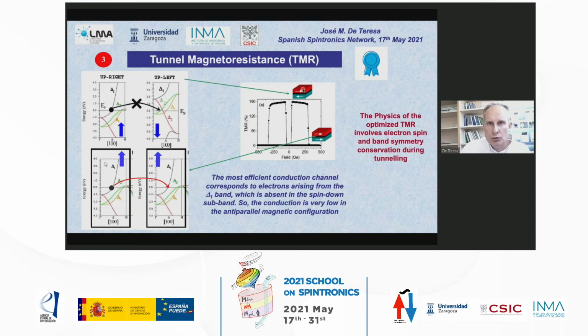So basically, to put it in a simple way, in these junctions, we have to take into account not only the spin conservation, but also the band symmetry conservation during tunneling. This was the difference that made these magnesium oxide single crystal junctions give this very large magnetoresistance of several hundreds of percent.